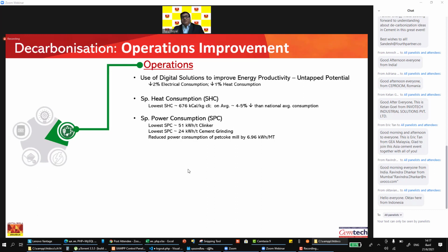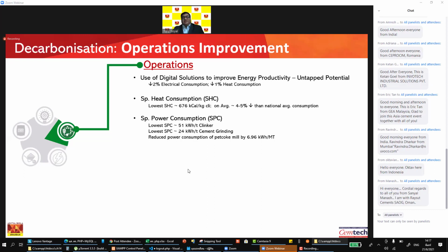global heat consumption, which is 4.4 to 5% lower than the national average consumption. In power consumption, up to the clinker, we have achieved a lowest of 51. Cement grinding alone is 24 kilowatt per ton of cement. And especially in pet coke milling, we have reduced our power consumption by 6.7 kilowatt per ton of material. In addition, we are focusing on our clinker factor reduction. We have achieved 38% clinker in our blended cement.